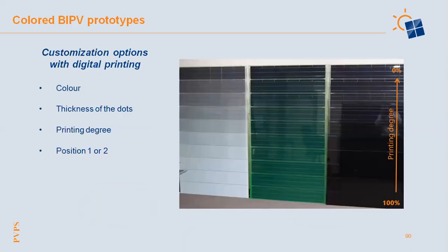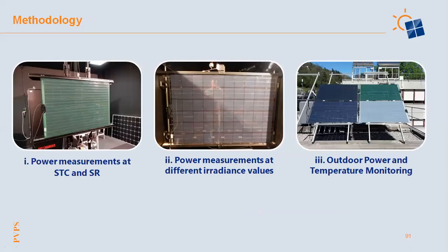And for this reason, we investigated different BIPV colored prototypes realized with digital printing and with different customization options. So we changed the color, we evaluated the change in the thickness of the dots. We changed the printing degree, as you can see here, from 100% to 0% to have a reference. And we changed also the position of the application of the color, from position 1 or position 2. In particular, we measured the power at standard test condition and the spectral responsivity. Also, we measured the power for different irradiance values, and we carried out the outdoor monitoring of power and temperature of some colored modules.